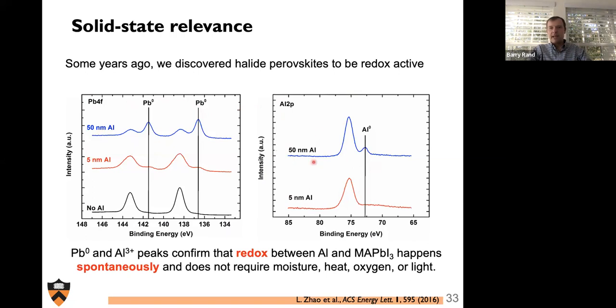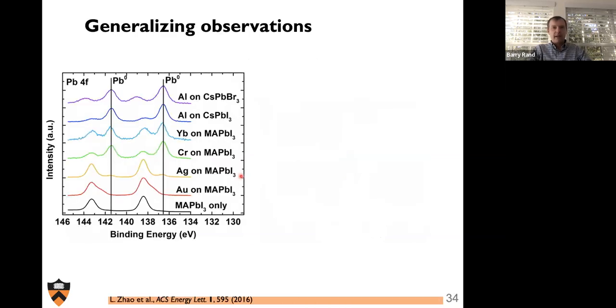Only at thicknesses of 50 nanometers aluminum do you start to see the remaining metallic aluminum. Otherwise, it's all consumed in this spontaneous redox reaction, making lead 0. What we showed was some generality of this: one, this happens regardless of whether it's bromide or iodide, shown here with cesium lead bromide or cesium lead iodide in the case of aluminum, and also that the ammonium cation played no role in the formation of lead 0. This was really an aluminum and lead 2 redox reaction. Using other low work function metals like ytterbium and chromium naturally led to similar results.